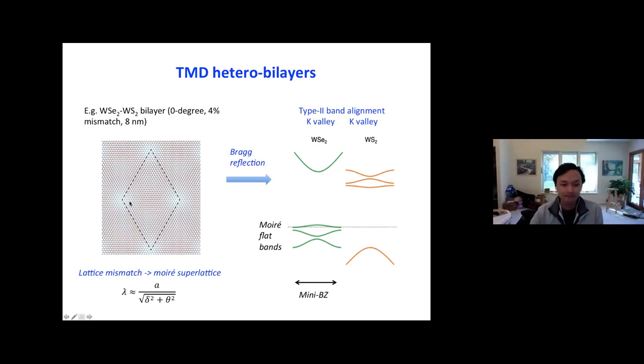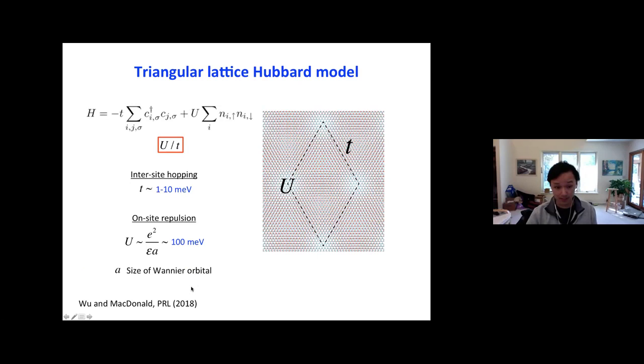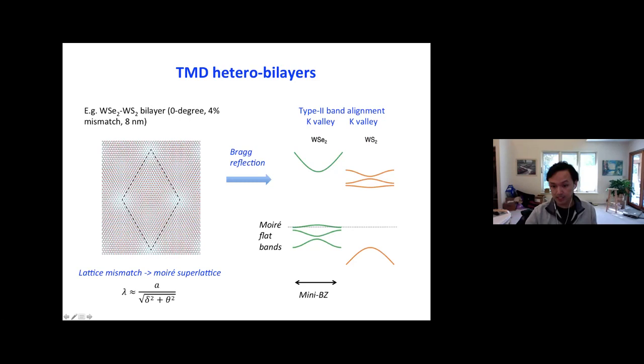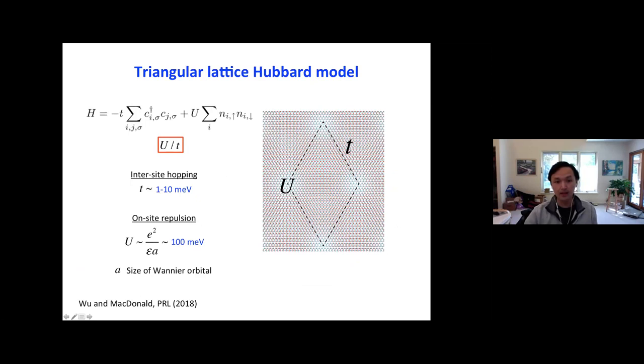So the moiré pattern will give rise to a Bragg reflection, and then produce the moiré flat bands and the mini Brillouin zone, which schematically looks something like this. Still, it's a type 2 band alignment, with the lowest energy conduction band in the WS2 layer, and the highest energy valence band in the WSe2 layer. Okay, and it's been shown by Allan MacDonald in 2018 that the low energy physics, if you can tune the Fermi energy of this system to say these moiré bands in the system, then it actually can be mapped to a single band Hubbard model.